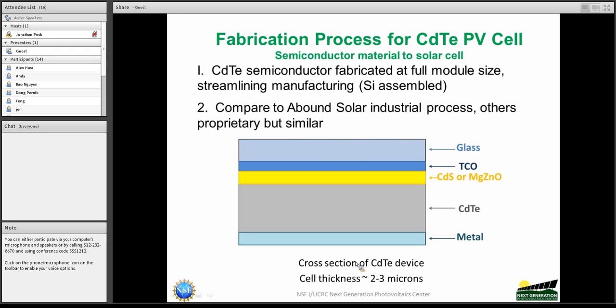And here is the cross-section of a cadmium telluride solar cell. It starts with a glass with a transparent conducting oxide. This particular glass and TCO are fairly low-cost soda-lime glass that is made on the float line. And the TCO itself is also made on the float line. Then there are two films that are grown on this glass. It has typically been cadmium sulfide till very recently, and we have found out that magnesium zinc oxide works a lot better than cadmium sulfide, and I will talk to you about that.